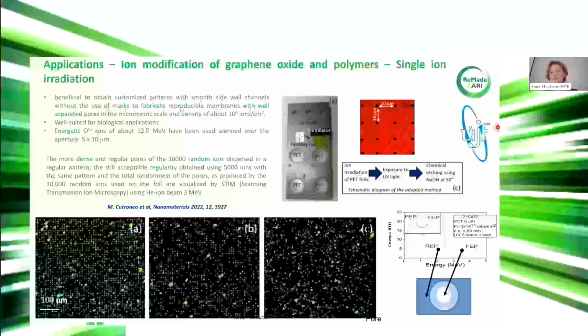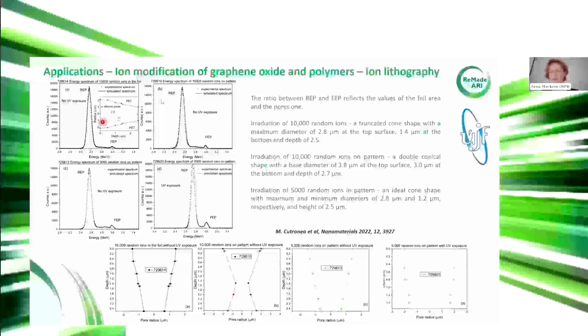After that, we have several possibilities: irradiate with UV light and use chemical etching. I have to say that before, this was a direct green method, I mean microstructuring of a membrane without any chemicals, without any agents. Now this is the first time we are using agents, I mean etching, to create the pores. It depends whether we use UV light and the etching procedure, or we do not use UV light.